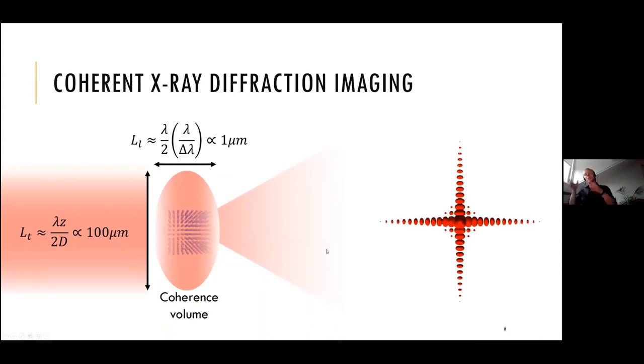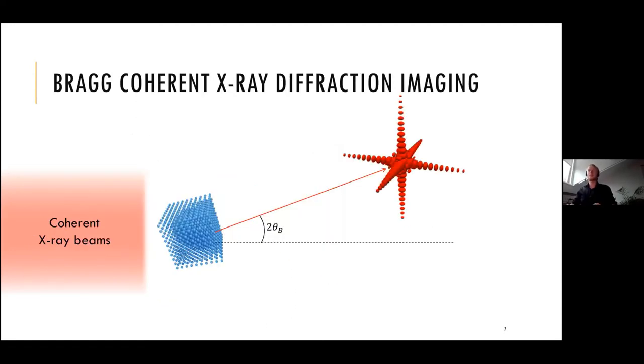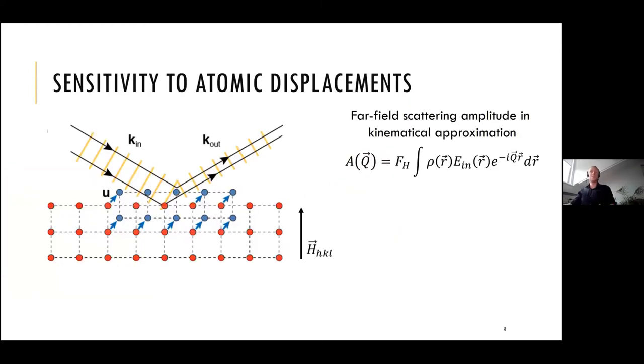So what is happening, basically, is we zoom in into one of those Bragg peaks if we go to the Bragg geometry. If we record the three-dimensional intensity distribution around the Bragg point, you will see something like that. They all look similar, but they have a different sensitivity, and that is the sensitivity to the displacements of atoms from their equilibrium positions. In this scheme, it's shown by the vector U, which is called the displacement field. If you shine your X-rays on a place where the atoms are displaced from the original positions, you get distortions in your diffraction pattern in one way or another.